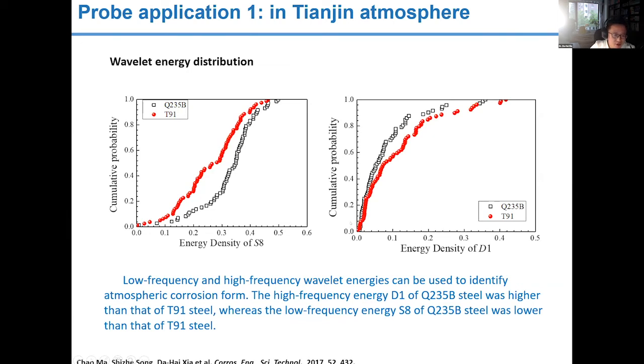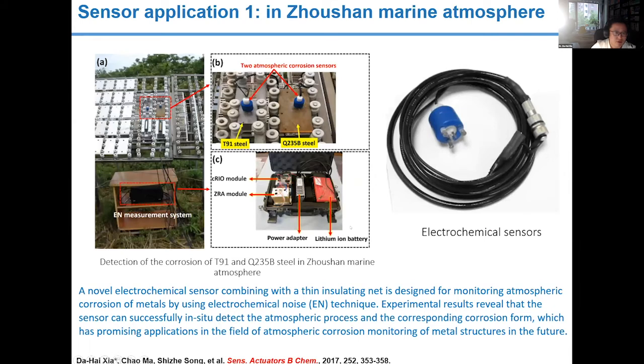Okay, we also use two sensors, as shown in figure B, to monitor atmospheric corrosion of Q and T steels in a marine atmosphere. So this is a picture of the field measurement. And figure B shows two sensors were placed on the surface of T and Q steels. This is a monitoring result, the noise resistance.